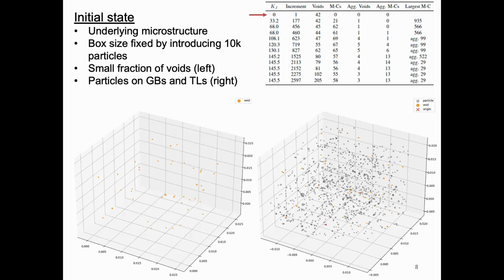We have 10,000 particles initially. A very small number of those are already voids, because you can see that also in the real material. So there is a certain number of voids initially. And these 10,000 particles are distributed along grain boundaries, triple lines, and inside the grains. What you see here is only the ones that are distributed on grain boundaries and triple lines. The underlying microstructure is not visible because it's too difficult to explain. So in the beginning, you have these voids here, and this is the picture of the voids and the remaining particles on grain boundaries.